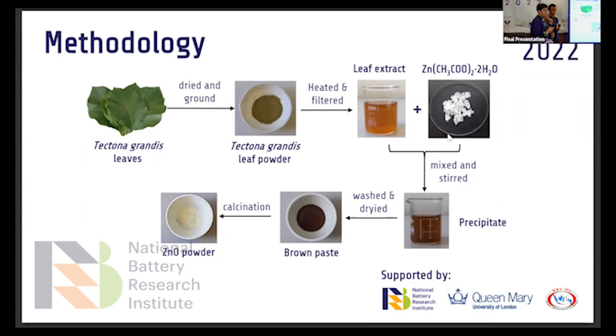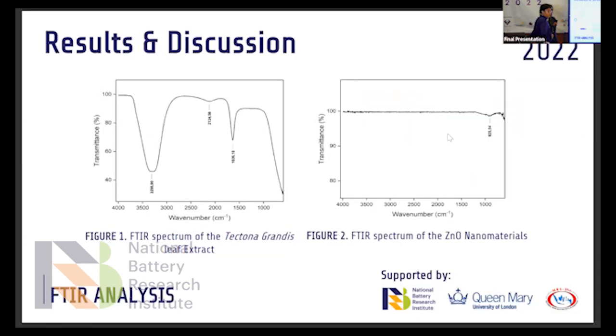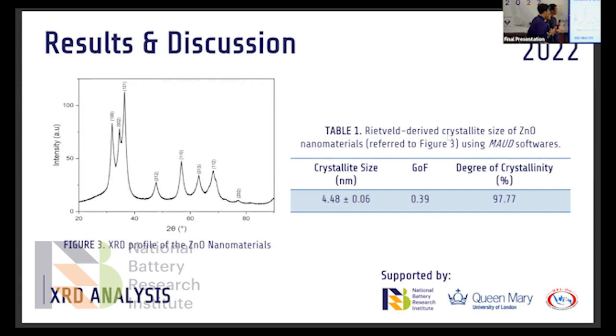So did you do the EDS? Yes. You do the SEM, scanning the microstructure? No, actually no. We just want to confirm. But how do you know that your material is nano? How do you determine? From the structure. Which structure? Crystal structure, the size. Crystallography. Can you go to the crystallography result? Yes. Crystallite size. Okay, so you obtained the crystallite size.